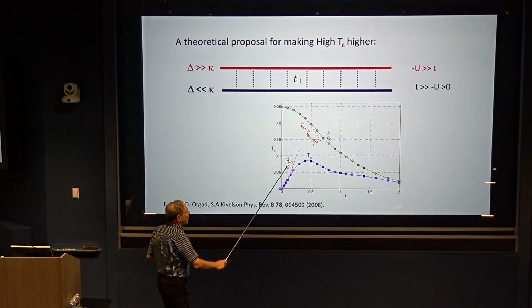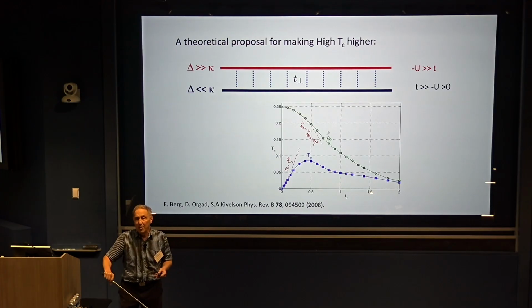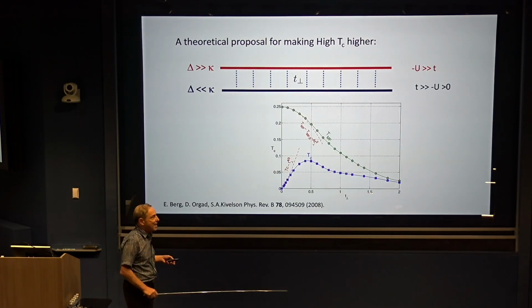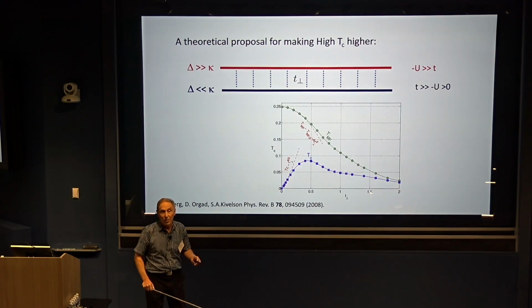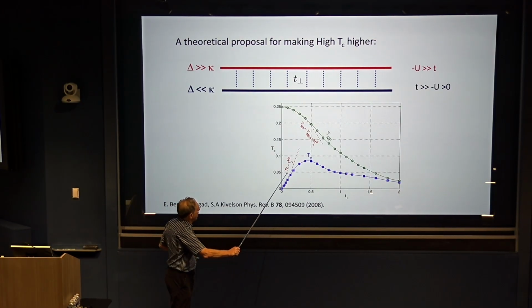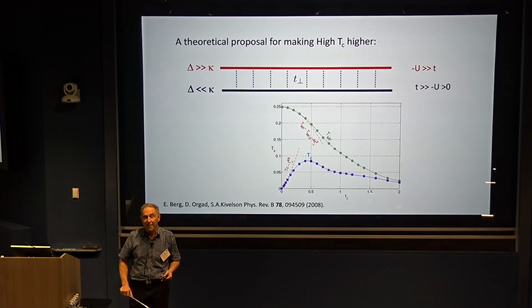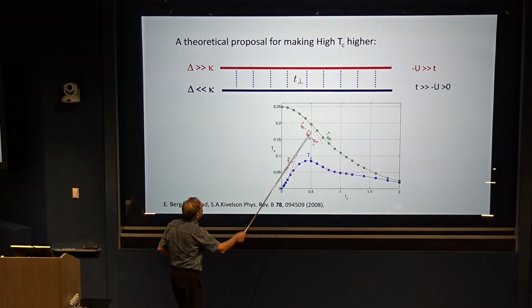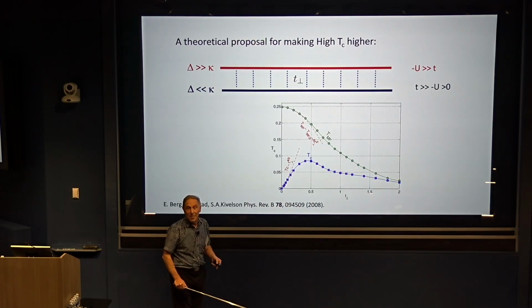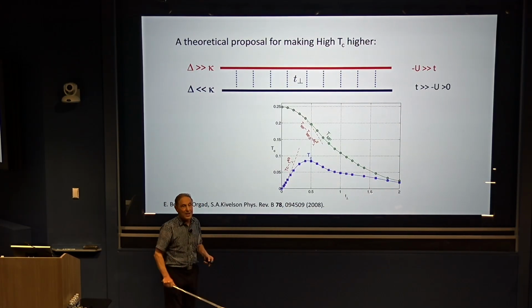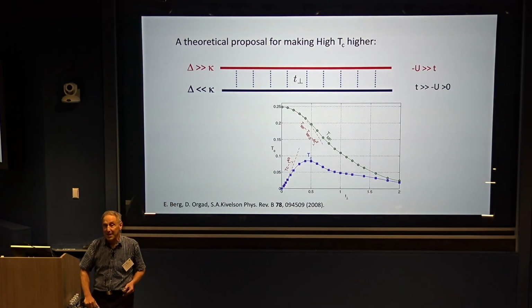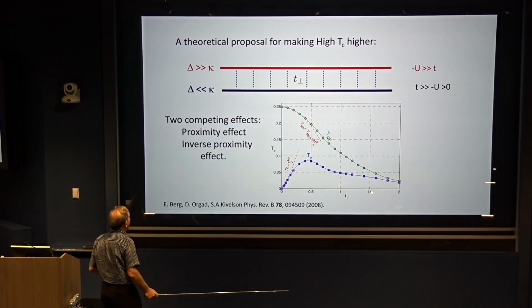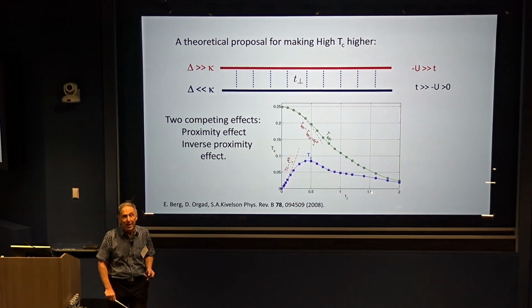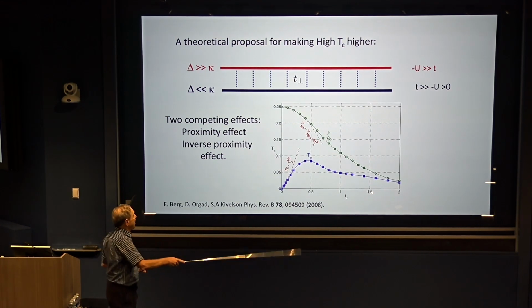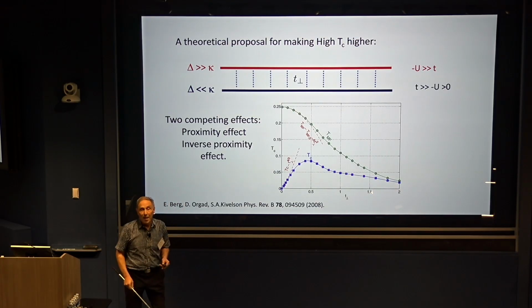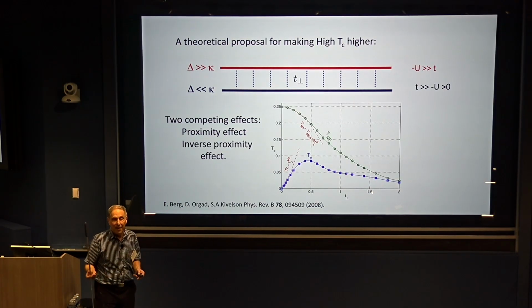But then we estimated what would be the actual TC by computing the zero temperature superfluid density and then asking when does the superfluid density equal TC, and that gave us this curve that first rises. That's due to the proximity effect, and then so inducing superconductivity in the metallic layer, and then the inverse proximity effect as the mean field TC drops. So it's two versions of the proximity effect working against each other, but it says that there is an optimal coupling between these at which maybe you could get a very high TC.